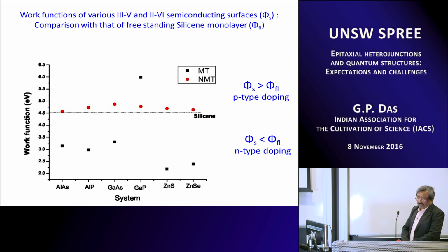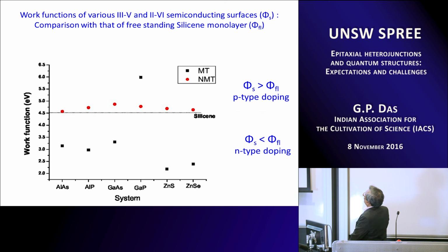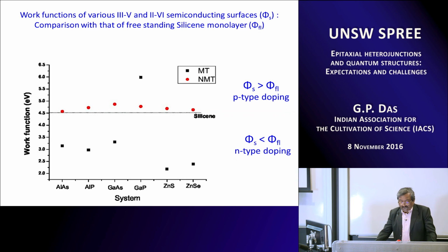Work function is something which is very important from the point of view of doping. So we did the calculation of the work function for the metal terminated as well as the non-metal terminated systems, and the ones with the red circle are the non-metal terminated systems, and you can see that the value of the work function is more than that of the freestanding. So it is a p-type doping. Whereas in case of the metal terminated, the black squares, the value of the work function is lower than that of the freestanding, and so it is the n-type doping.